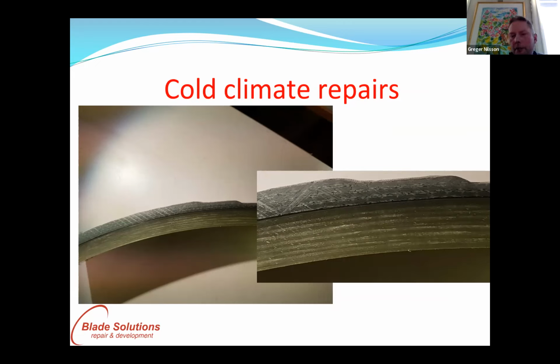If you think of a laminate, if it's minus 20 degrees outside and you have minus 20 degrees on the surface, in the interface between the laminate and the repair, it's impossible to do the repair. If you do, you have to put some heat in it. Normally you put heat from the outside, but that means you have a variation of the heat through the repair part. So if you're going to do a vacuum infusion for a structural repair, you will have different viscosity depending on what temperature you have in the specific part of the repair.